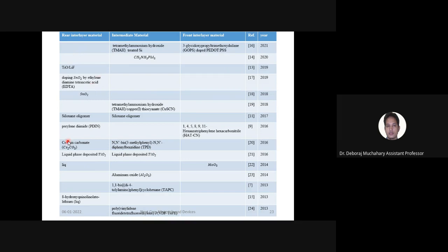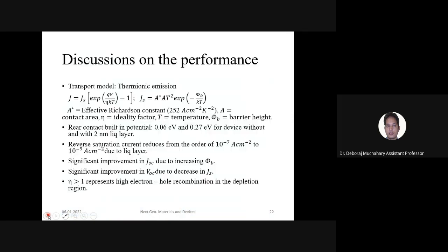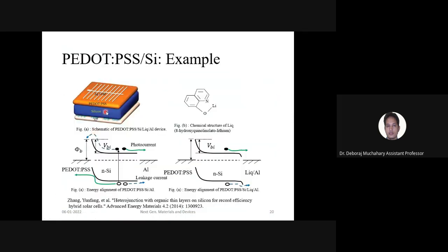that lots of materials are used at the rear interface, as intermediate materials, and as front materials. So what this means is that if you have inserted something in between this heterojunction, that means there will be some front layer, that is called front interlayer. I'm saying it front interlayer. If you are inserting something here, there is rear interlayer. And if you are inserting in between this silicon and PEDOT:PSS, then it is intermediate layer. If you are inserting between silver and PEDOT:PSS, this is front interlayer.